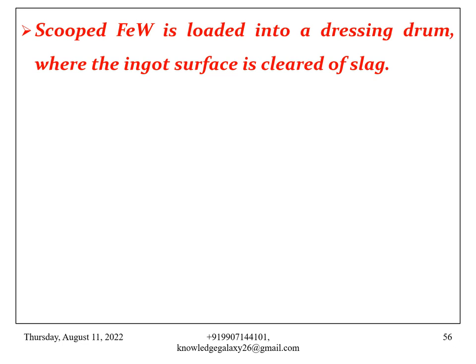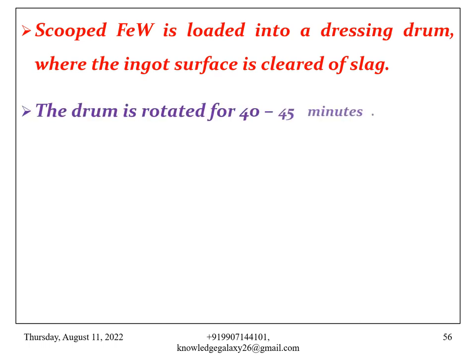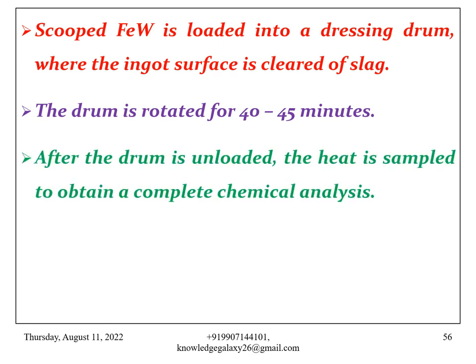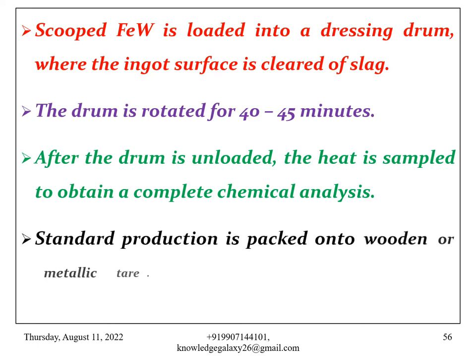Scooped ferrotungsten is loaded into a dressing drum where the ingot surface is cleared of slag. The drum is rotated for 40 to 45 minutes. After the drum is unloaded, the heat is sampled to obtain a complete chemical analysis. Standard production is packed onto wooden or metallic trays.